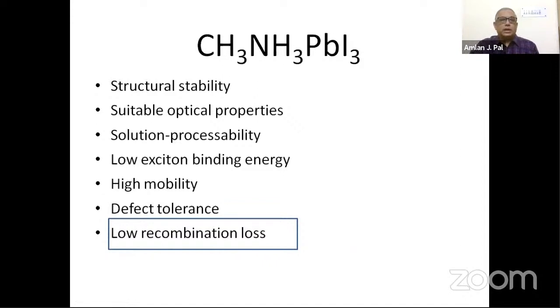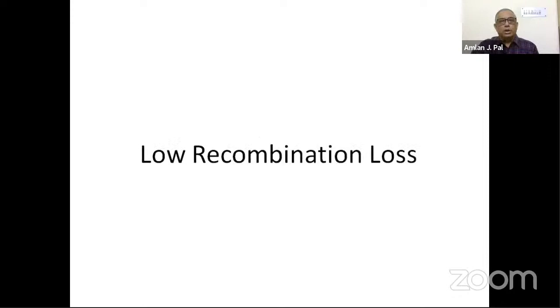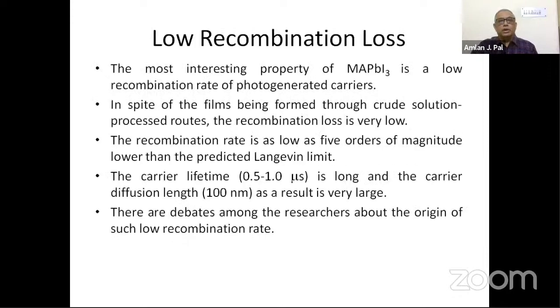Because, as I said, in any solar cell, of course, you can separate charge carriers, but as soon as you separate the charge carriers, they immediately recombine, and they do not go towards the opposite electrode. But thankfully, in this material, the recombination loss has been found to be very low. Why? That is really a wonderful thing. That is why this material's recombination loss is so low.